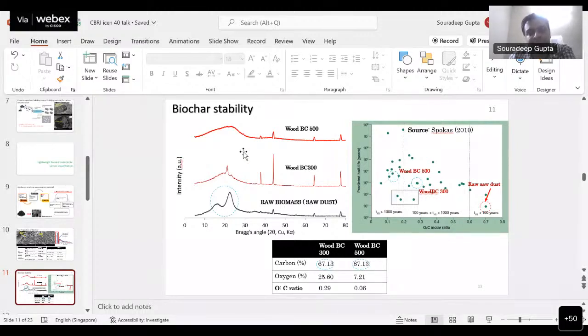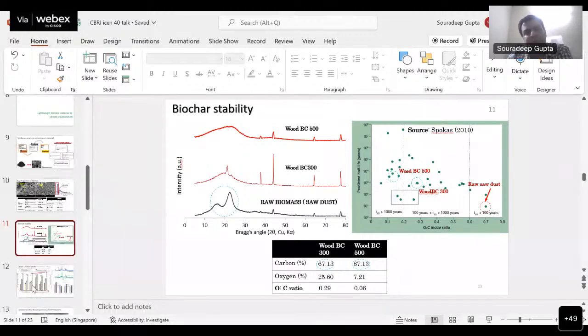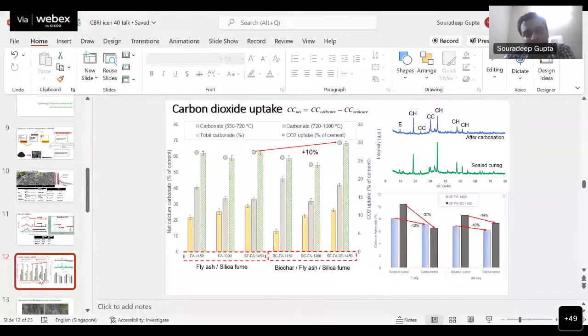And this kind of biochar will remain stable in the alkaline environment. Spokas, in 2010, published a chart relating the predicted half-life, or you can call it the stability, of biochar to the oxygen to carbon molar ratio. Based on that, wood-based biochar produced at 500 degrees can have a half-life of about 100 to 1,000 years, right? This will, of course, depend on the carbon content of the biochar, which depends on the preparation condition. So how does it perform when it is added to lightweight building materials?